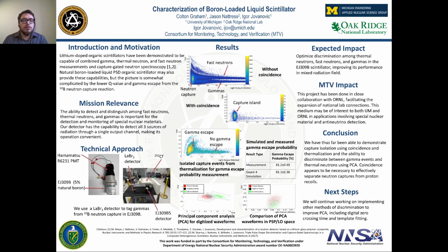In the top of the results, you can see the PSD histogram without any coincidence, and you can see the capture island is very much so bled into the fast neutron and gamma region, making isolating captures using traditional PSD impossible. However, by enforcing coincidence in the lanthanum bromide detector, we're able to much better isolate the captures, which you can see shown here.